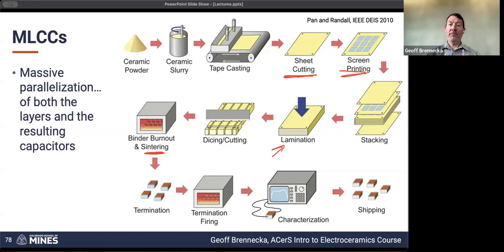And if you get a short circuit, then the material is dead, either because it just can't store charge at all, or if it stores a little bit and then short circuits and ends up creating damage, maybe you get a lightning bolt and it zaps the entire device that it's sitting inside of. So if we're going to sacrifice the continuity of either of these layers, we want the metal to be a little bit less precious than the dielectric. The good news is that most of the metals that we're using are reasonably ductile, especially at the sintering temperatures, and especially compared to the ceramic layers.